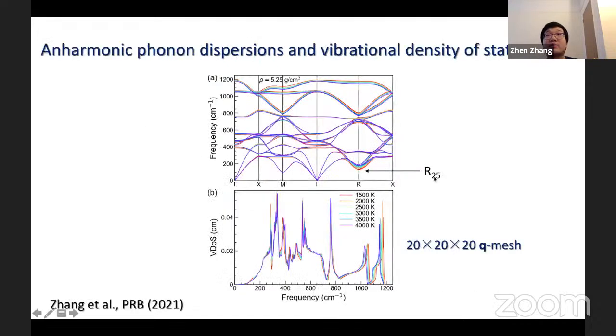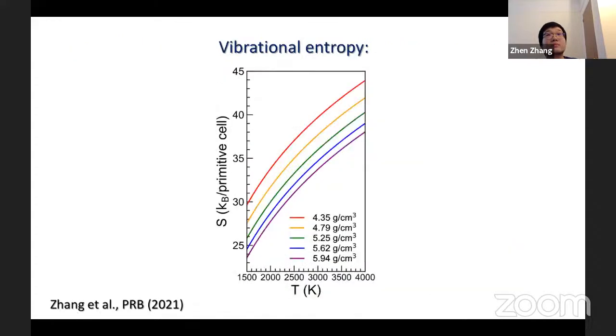Here are the obtained temperature-dependent phonon dispersions. The R25 mode with imaginary harmonic frequencies now has a well-defined phonon quasiparticle with real frequency. The vibrational density of states were obtained with a dense converged 20 by 20 by 20 Q mesh. Then vibrational entropy was computed using these temperature-dependent vibrational density of states.